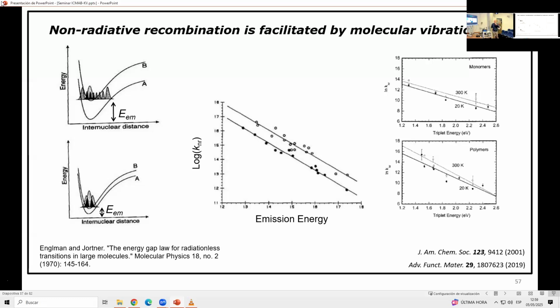It's called the energy gap law for radiationless transition, known since the 70s. So at low gaps, in a recombination event, it's easier to dump the energy into a vibration of the molecule rather than a photon. So what happens is that the molecules just vibrate instead of emitting light. And this is because it's a carbon and not a heavier atom which likes to stay in place.